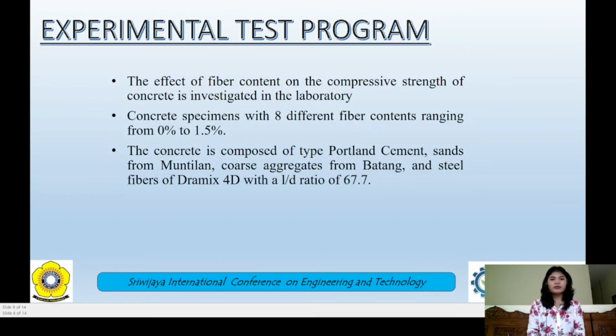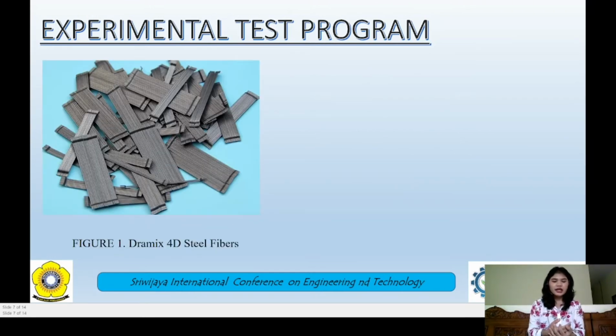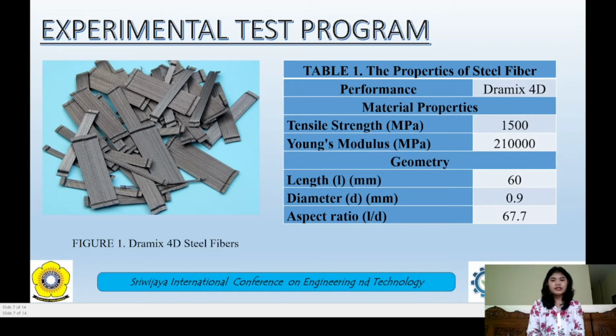The second point, experimental test program. The effect of fiber content on the compressive strength of concrete is investigated in the laboratory of civil engineering, Diponegoro University. Concrete specimens have 8 different fiber contents ranging from 0% up to 1.5%. The concrete is composed of Portland cement, sand from Muntilan, coarse aggregate from Batang, and steel fiber of Dramix 4D with aspect ratio 67.7. Figure 1 shows the shape of steel fiber used, namely end-hook steel fiber. Table 1 shows the properties of steel fibers, including material property and geometry.